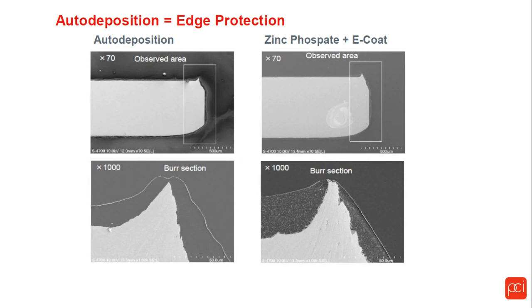From an edge protection standpoint, there's also a benefit. If you can see these photos, they're showing auto-deposition with a zinc phosphate and E-coated part. The burr sections, as you can see on the bottom section here, with the auto-deposition, the coating follows the contour of the part, including the burr. With the E-coated part, you were seeing some pinhole corrosion from parts if subjected to salt spray.